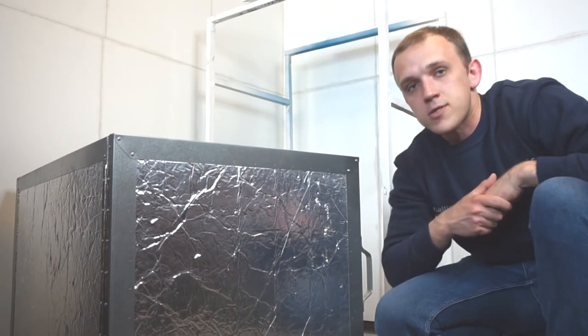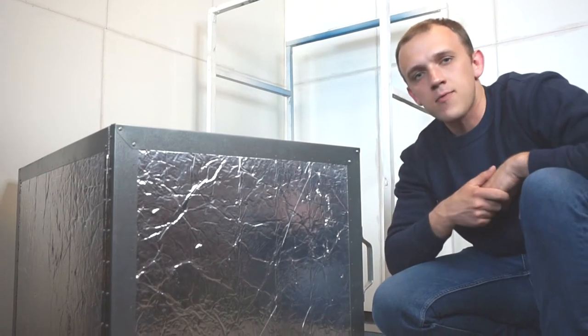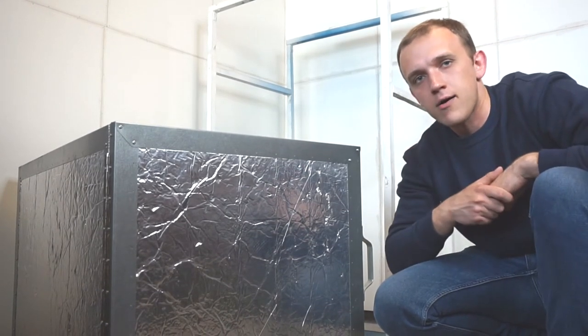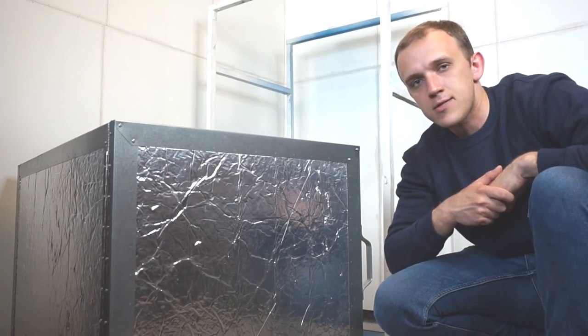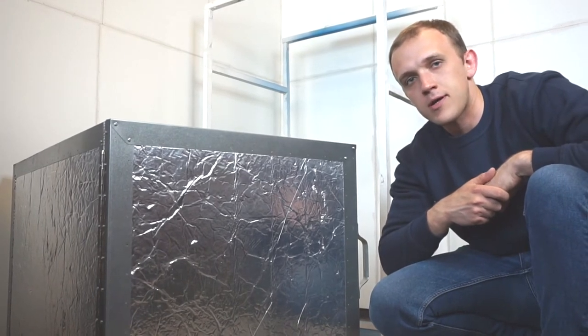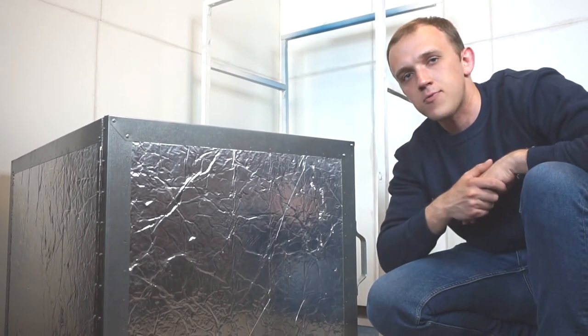My oven was already hot so next I will wait for it to reach 180 degrees Celsius and then I will wait for 20 minutes for powder to finally cure.